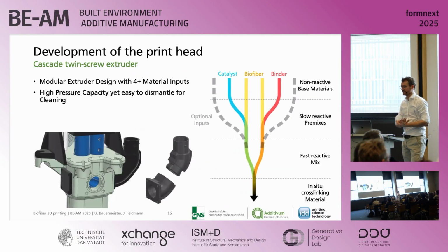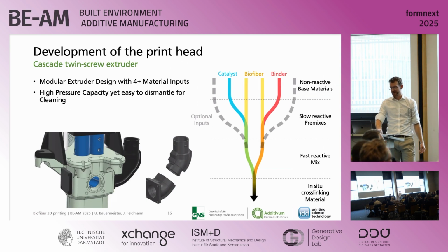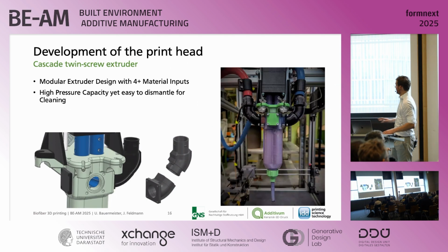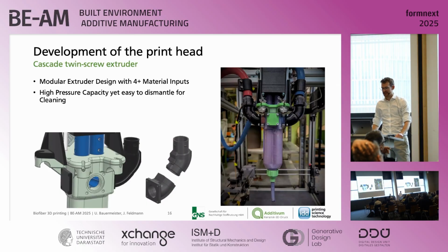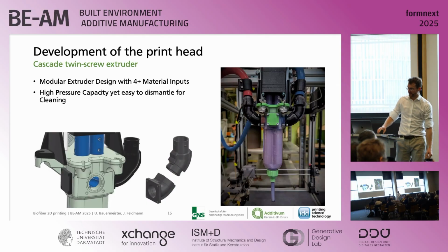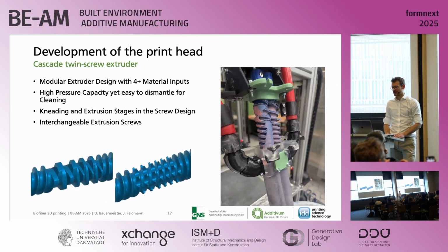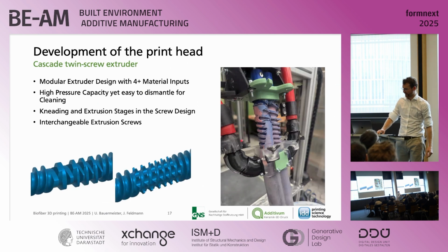So we came up with a design for that, for 4 or more materials as an input, and we needed it to have high pressure capacities, and it should be easy to dismantle because it's not as sticky anymore, but it's still sticky. And here you can see that in action. This is an experimental print head. Here we mixed 2 white clays with dye, red and blue. And you can see a nice purple color coming out at the bottom, so that worked fairly well. We also looked into different designs of screws, because they have 2 jobs. One is to push the material out of the small nozzle, and the other is to mix the sometimes longer fibers well with the catalyst and binder. So we can interchange them depending also a bit on the size of the fibers, for example.